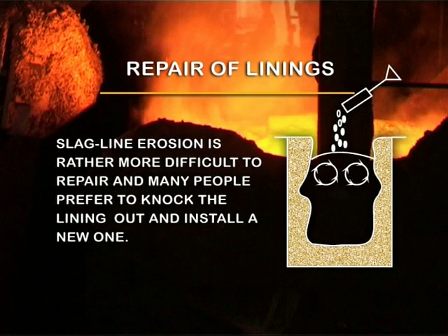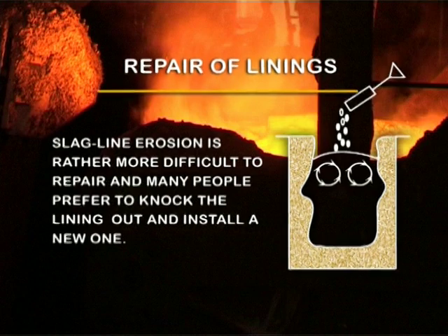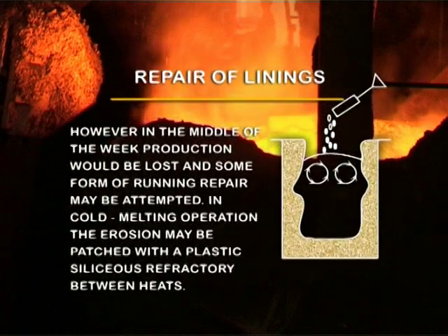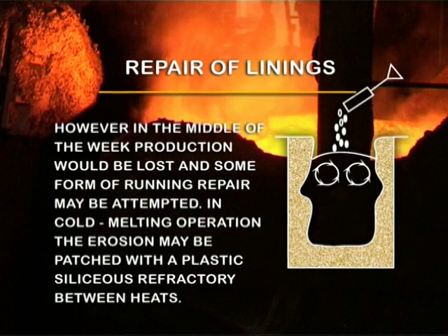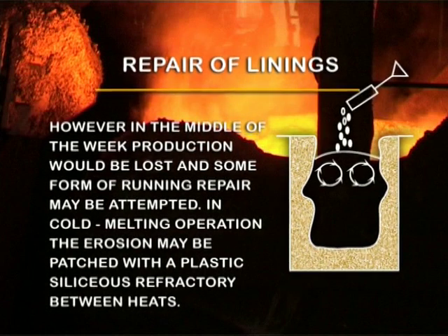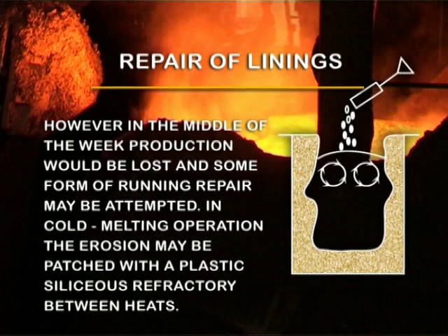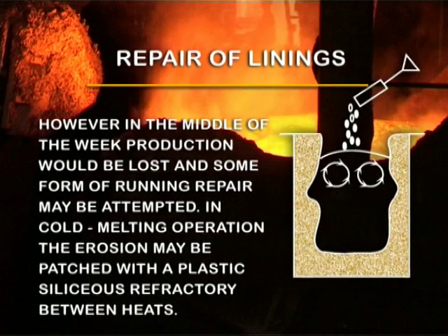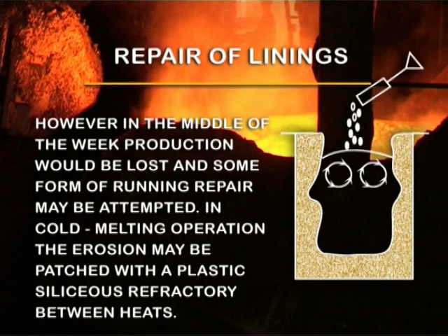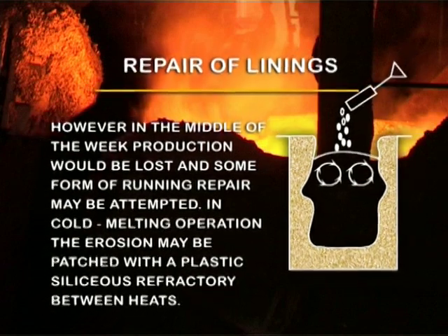Slag line erosion is rather more difficult to repair, and many people prefer to knock the lining out and install a new one. However, in the middle of the week, production would be lost and some form of running repair may be attempted. In cold melting operation, the erosion may be patched with a plastic siliceous refractory between heats.